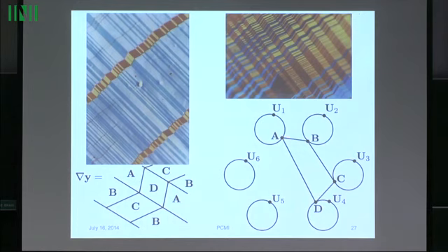Bottom line is that A is rank 1 connected to exactly 2 matrices over here. Okay? I'll choose one of them, B. And then B, it turns out these 2 wells are rank 1 connected too. So B is rank 1 connected to exactly 2 matrices over here. I'll choose one of them, C. C is rank 1 connected to exactly 2 matrices over here. I choose one of them, D. And now the magic happens. If I make exactly the right choice of these wells and exactly the right choice of those rank 1 connections, I had some choices, and then D turns out to be exactly rank 1 connected back to A, okay?